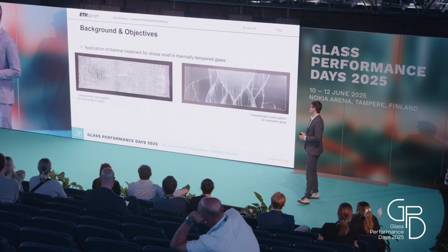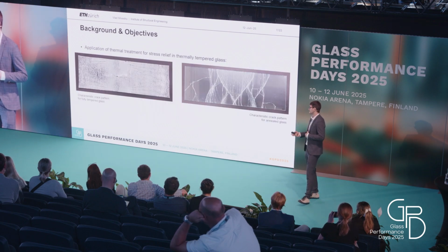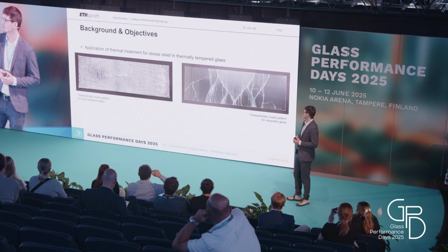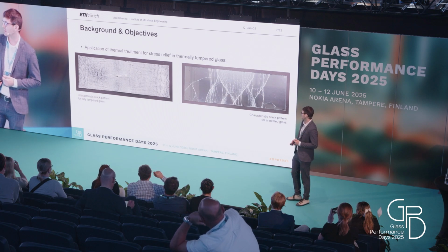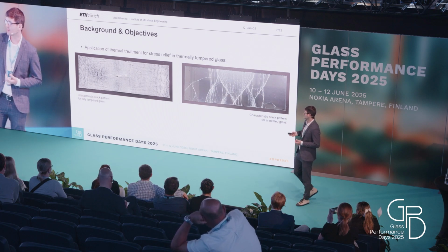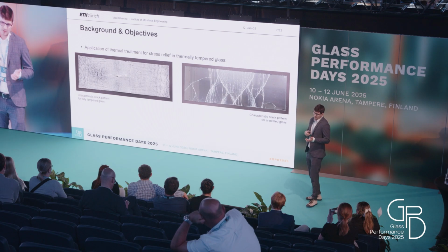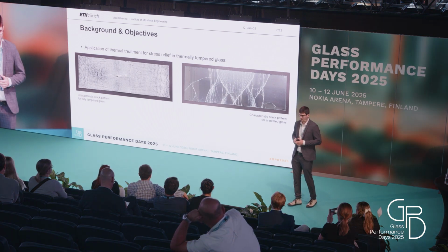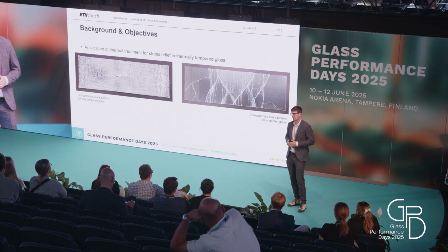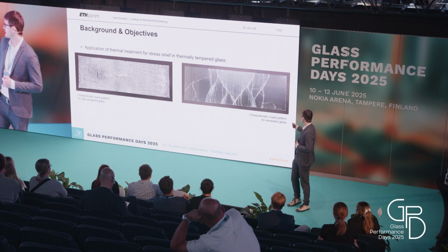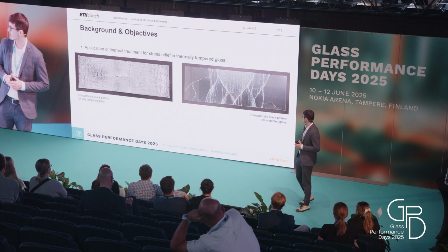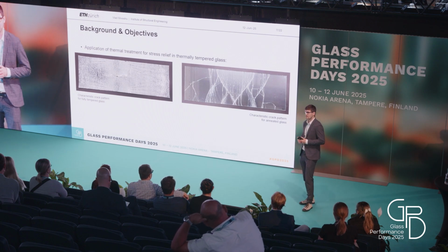Today, I would like to focus on the other issue, which is the stress relief. The characteristic crack pattern of fully tempered glass is the one that you can see on the left. What we need mostly for cutting the glass is a crack pattern that is characteristic for annealed glass with larger fragments.